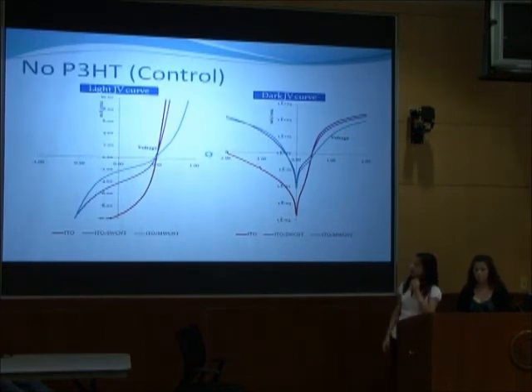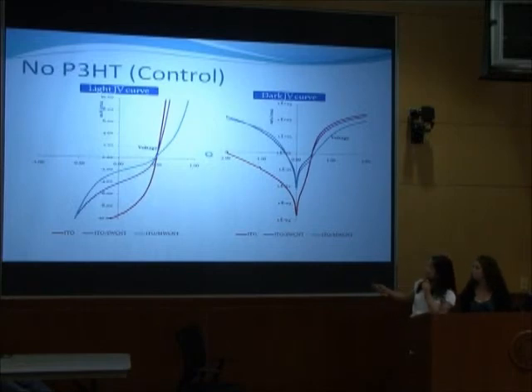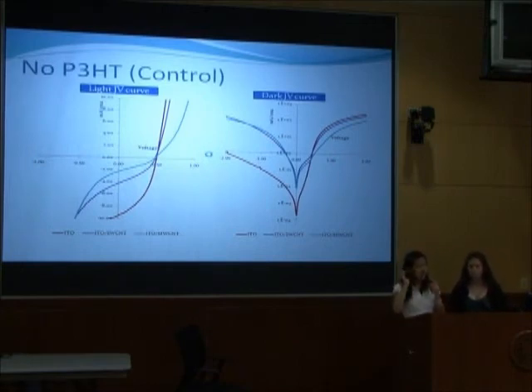So what we have here is a solar cell voltage-current graph. This is what we use to determine the efficiencies of our solar cells. In a nutshell, what you want to see is this deep curve inside the 4th quadrant. This indicates that a lot of power is being generated. Conversely, on the dark current-voltage curve, you want to see an asymmetrical behavior because in the dark, a solar cell is supposed to act like a diode. If the dark curve is symmetrical, it means that the device is shorting or that the charges are bypassing the transport layer, which completely defeats the purpose of a solar cell.